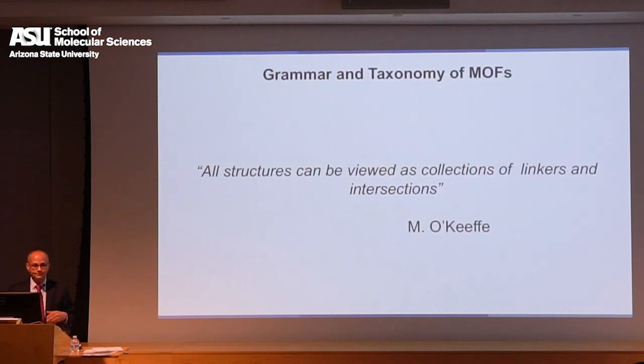Okay, so we showed the feasibility of making MOFs in crystalline form. We showed that you can take the interior of the MOF out and use the space inside. Okay, this then was an emerging new field because anything a chemist can imagine, now we've shown that you can make. So it was time to sit down and put a really thinking basis for the field in terms of which geometric unit could give you which structures. And of course, you can imagine there's an infinite number of structures that could be made in this way, depending on the geometry.